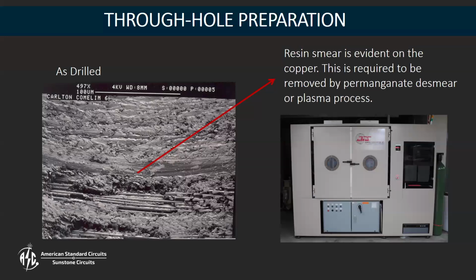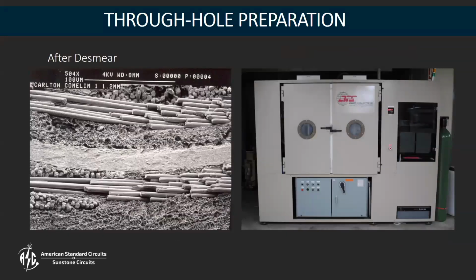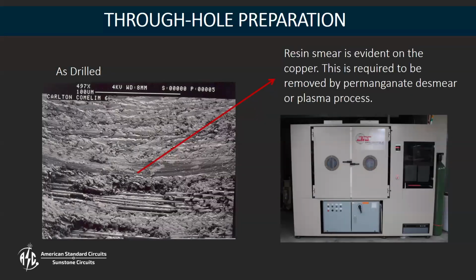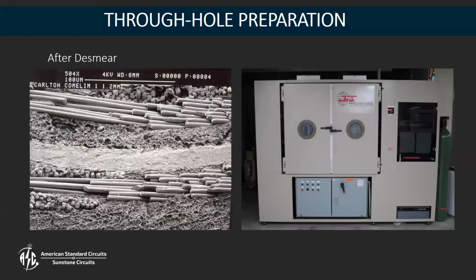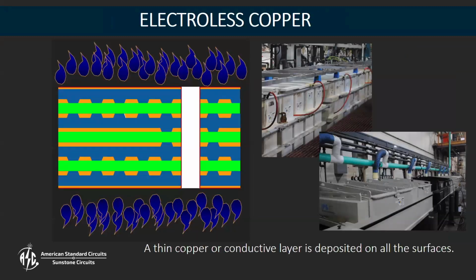So that's what it looked like before and after. You can see before you've got kind of a messy look to your copper post. And then after the desmear process, it looks nice and clean. You can see your copper, you can see your glass fibers, and you can see your epoxy in there. So that creates a nice, clean hole ready for copper deposition.